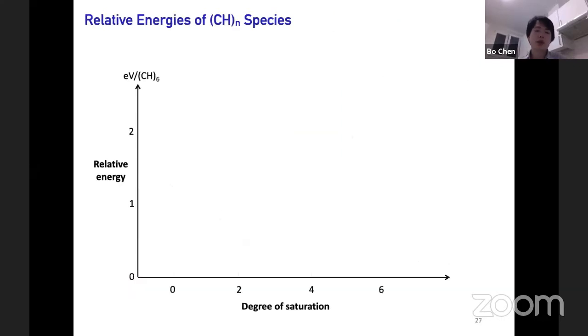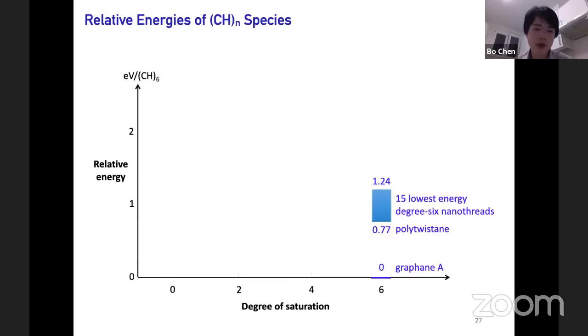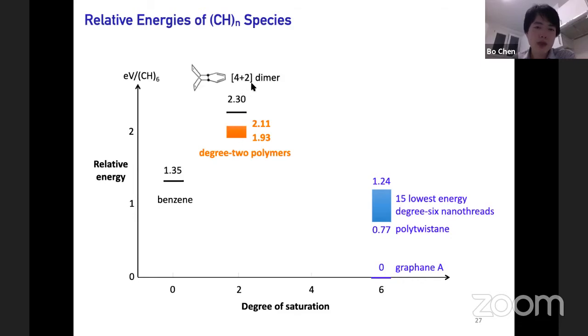So now that we have degree 2, degree 4, degree 6 threads, it would be interesting to compare their energies on the same graph. Graphane, which has the same CH stoichiometry, turns out to be the lowest energy structure for the CH species. Degree 6 nanothreads are higher, but not by too much. And benzene is here. Degree 2 is here in this narrow range. And this is a 4+2 dimer, so it's not a polymer. And this is going to be important in the initiation process. Its energy is higher. Degree 4 is here.